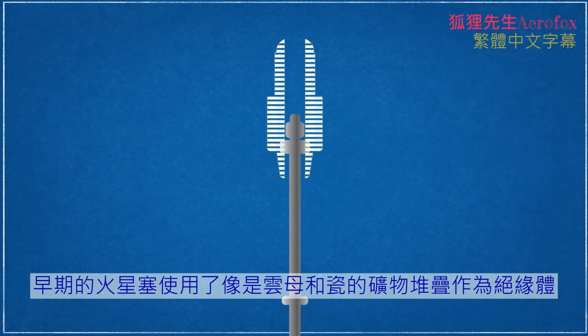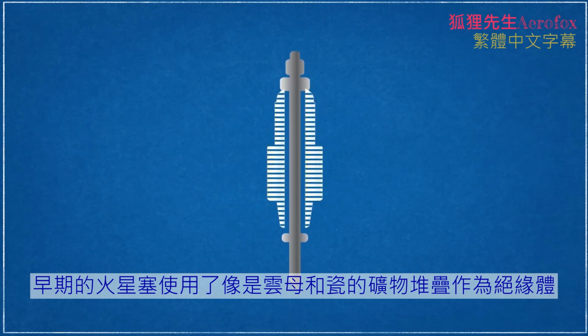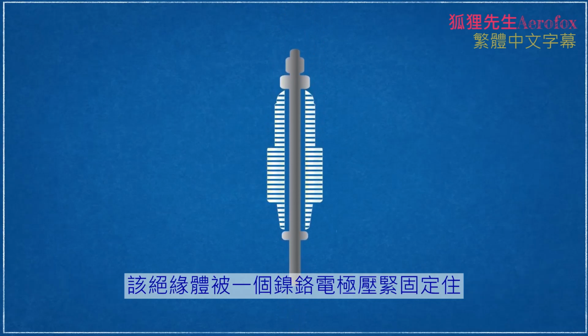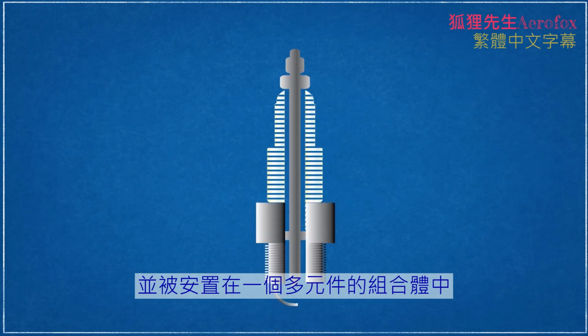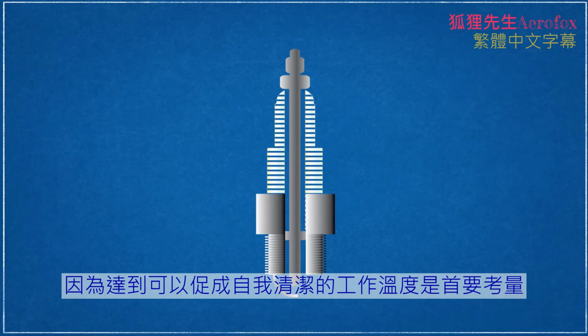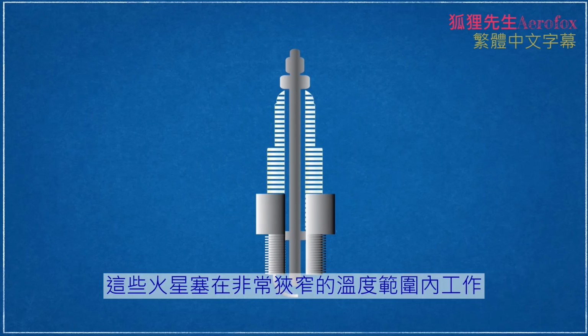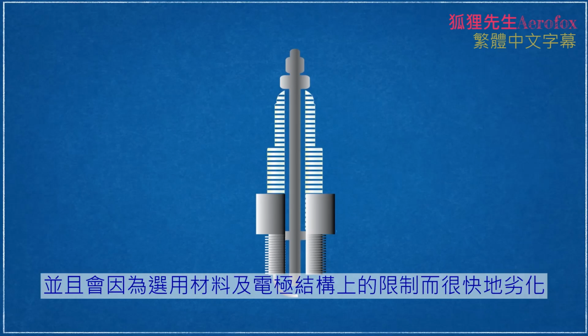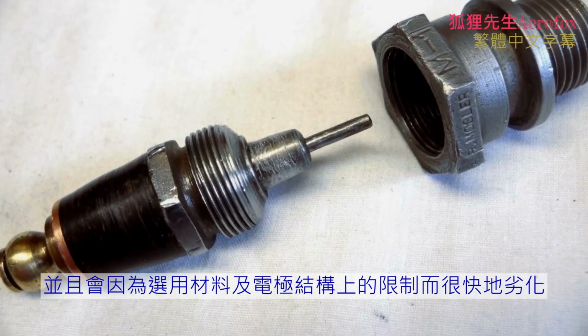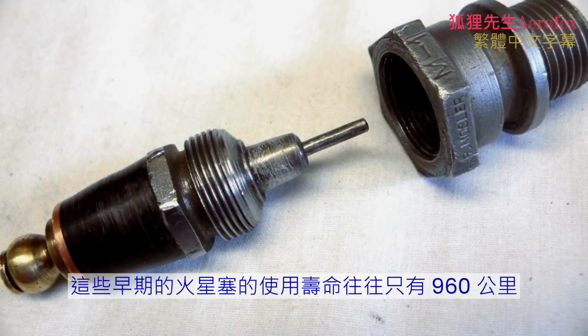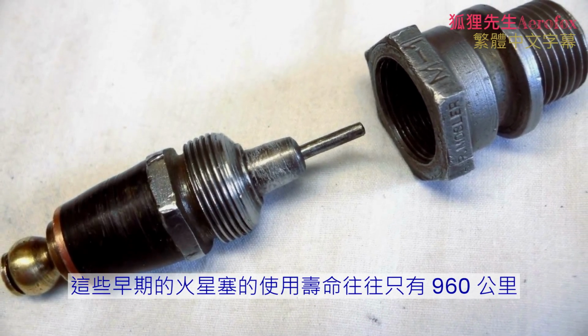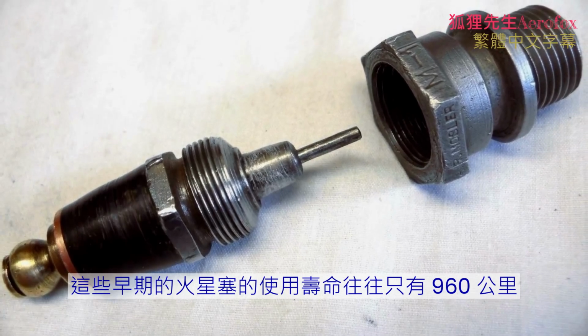Early spark plugs used a stack of minerals such as mica or porcelain as an insulator, which was compressed and held in place by a nickel-chromium electrode and housed in a multi-piece assembly. Because achieving operating temperatures that promote self-cleaning was the primary concern, these plugs operated at a very narrow temperature range and degraded rapidly due to limitations of the materials used and the electrode's construction. It was common for these early plugs to have lifespans of just 960 kilometers or about 600 miles.